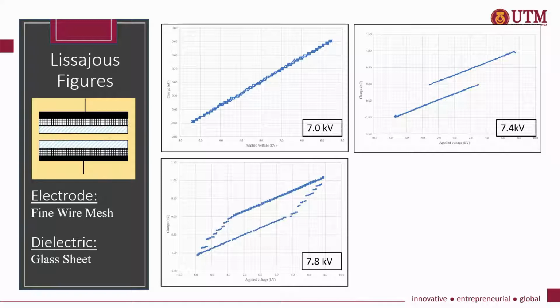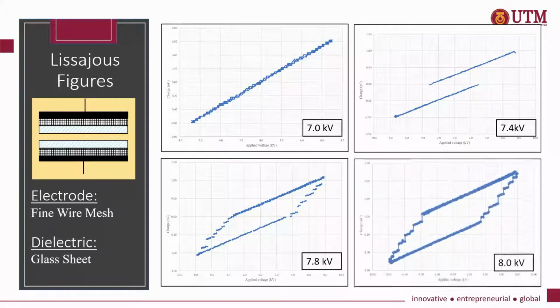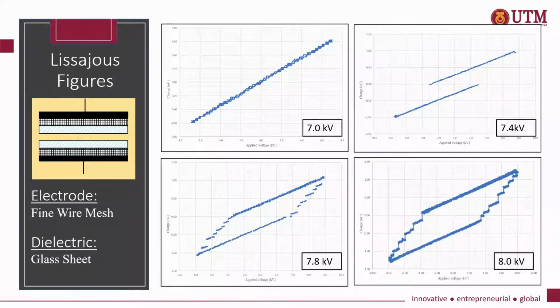And the third figure indicates a mixed glow filamentary discharge by the staircase-like regions of this waveform at 7.8 kV of the applied voltage. And finally, the waveform turns into a regular parallelogram where there is the presence of the connecting lines in the staircase-like regions, which indicates a pure filamentary glow discharge at 8 kV.